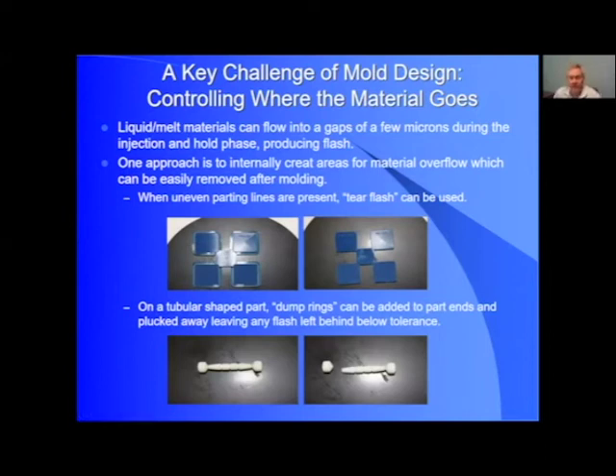So one of the key challenges in designing an effective injection molded drug component is controlling where the material goes. We're dealing with melted liquid materials that can be relatively low viscosity and can flow into very small gaps. And so even a few microns during the injection mold can cause it to leak out of the mold and produce what we call flash, which is basically flimsy, filmy material that's not part of the desired finished dimensions of the products. And again, if you don't design your mold properly, you can build up high pressures in parts of the mold that force the mold open and create additional flash.